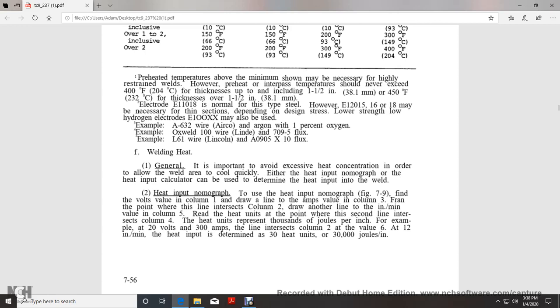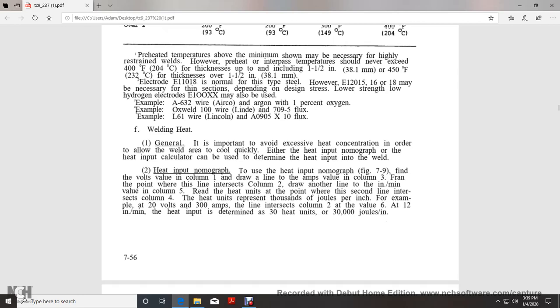To use the heat input nomograph, find the volts on column 1, then draw a line with the amps value of column 3 and mark the point where the line intersects column 2. Draw another line with the inches per minute value of column 5 and read the heat units on column 4 at the point where the second line intersects. Heat units represent thousands of joules per inch. For example, 20 volts and 300 amps give a line intersecting column 2 at the value 6. At 12 inches a minute, the heat input is determined to be 30 heat units, or 30,000 joules an inch.